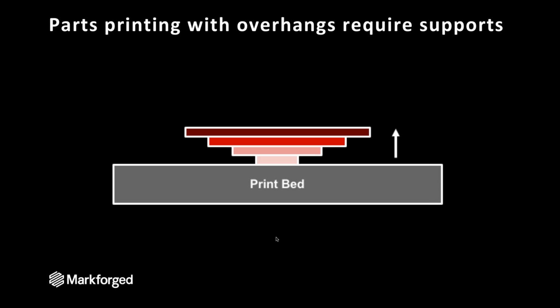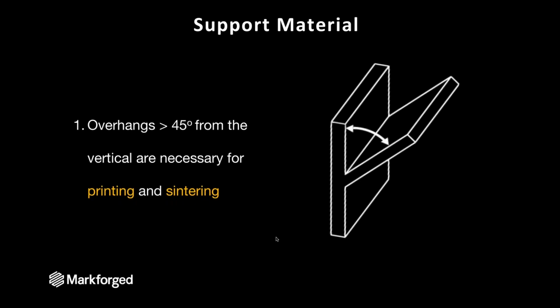Sometimes it's really important to have a lot of supports, other times it's not. I can give you some base details, but this process is very geometry dependent, and you're probably going to have to play around with it to really get the part, orientation, and geometry that works for our process. So this is an example of support material. Everything over 45° from the vertical requires supports for both printing and sintering. Sometimes our part will generate supports that maybe are not necessary for printing, but they definitely are for sintering. Because again, if you think about it, there is that gravity and heat aspect that goes into these parts that may cause it to warp or slump.